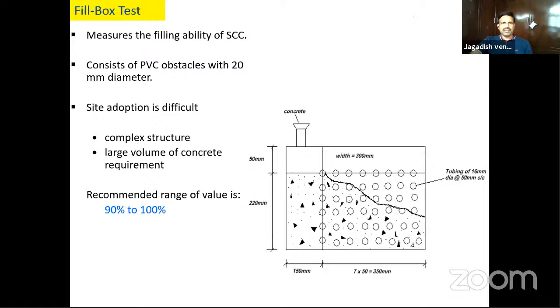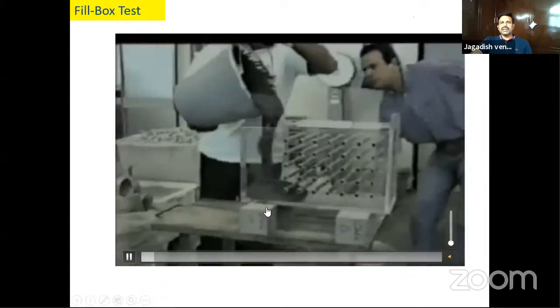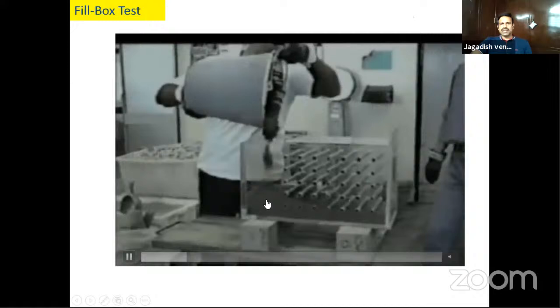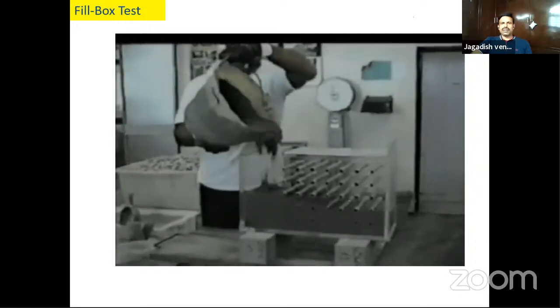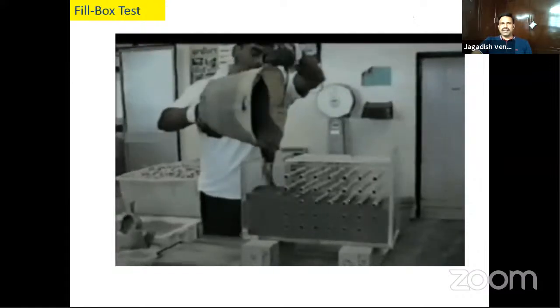Next is fill box test. Initially, we also made a fill box, a box to test initially. I'm talking about 2002. So the box, you fill it using SCC, and it should flow through these reinforcement, and it should fill. That means it should fill between 90 to 100%. How it is, you can see here. One side you are pouring the SCC, and it is passing through the obstacles, the congested obstacles we created. And the filling percentage should be 90 to 100%. You can see here. It should be completely filled. If the concrete is good, the value will be between 90 to 100%. So this is a fill box test.